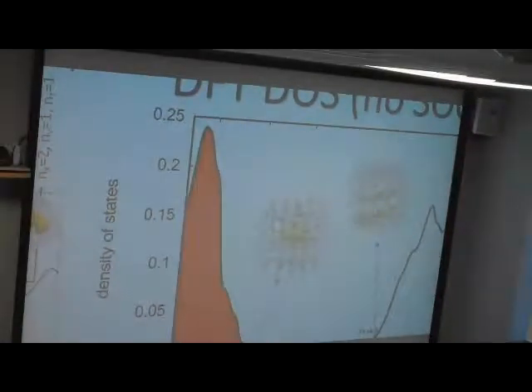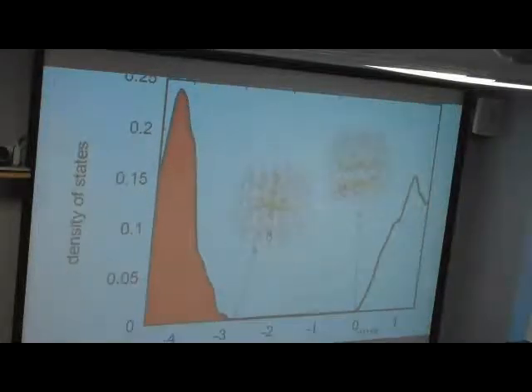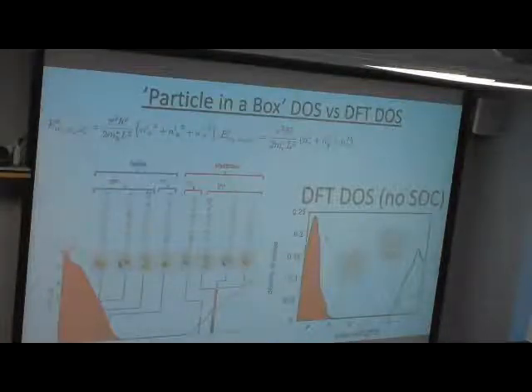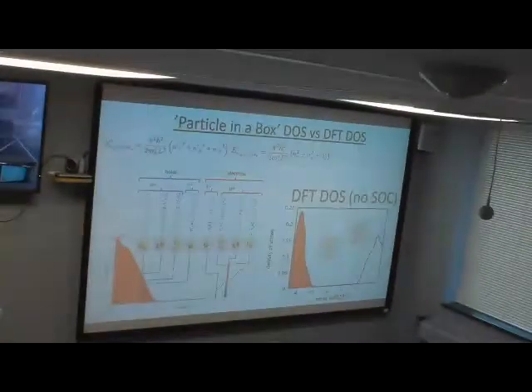Yeah, because you only get it across the faces of the 1-0-0 or 0-1-0 of all the crystal faces. So it seems to take a spherical shape. The LUMO is less spherical. Yeah, less spherical. It might be a signature of some kind of, maybe not really a defect state, but maybe some kind of surface state, maybe.